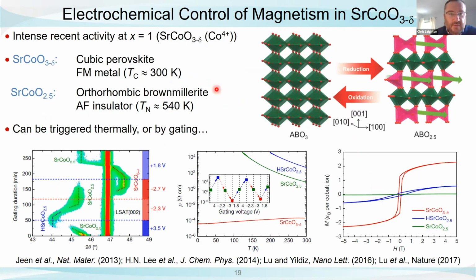In particular, x equals 1. So this is one of the end members of this compound. I mentioned to you that it's a cubic perovskite. It's ferromagnetic with this around-room-temperature TC. But also there's this really beautiful gift, which is if we make it oxygen deficient to the level of half an oxygen per unit cell, it turns out there's a vacancy-ordered phase that forms. It's called orthorhombic Brownmillerite, and it couldn't be more different magnetically. It's an antiferromagnetic insulator. And one can drive this transition with gating back and forth between the perovskite and the Brownmillerite, between a ferromagnetic metal and an antiferromagnetic insulator.